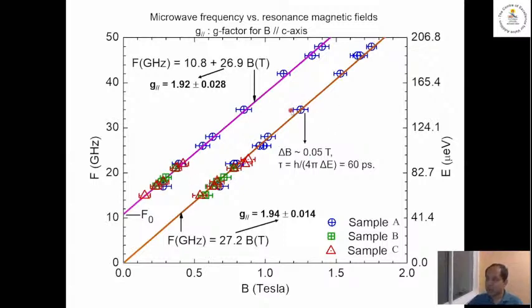And then from the width of the resonance, remember we had a resonance with some characteristic width. The width was about 50 millitesla, and we're going to get a spin lifetime of about 60 picoseconds. One of the things about graphene is that in principle it could have a very long spin lifetime, but in our experiment we didn't quite see it. Another remarkable thing is that normally in spin resonance you just get one branch, but we're seeing two branches, and further, one of these branches has a finite intercept.